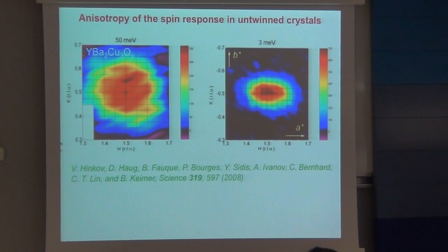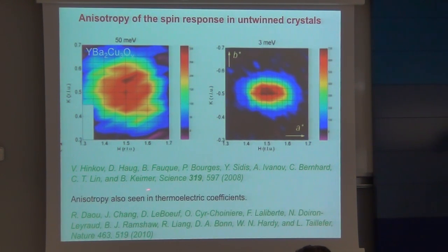So they reported that this meant that the spin response of this YBCO superconductor mimicked the charge response, and it seemed to be evidence for microscopic lowering of the symmetry within this state. And then there's been some work on thermoelectric coefficients led by Taillefer's group in Canada, which also confirmed that this anisotropy sets in. So I think in the high Tc materials, certainly in yttrium barium copper oxide, it's now widely accepted that there is some form of an electronic nematic state in the phase diagram near the superconductivity. And we'll come on later to the relationship that that might have with the superconductivity.